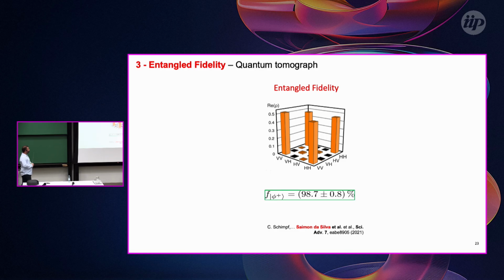Okay, the third thing that we look at is the entanglement fidelity, which is measured by doing quantum tomography. In general, we already know that these gallium arsenide quantum dots generate a Bell state, the phi plus. Generally, with this fidelity you want to measure what your experiment is giving you compared to what we are expecting. This means we have a Bell state, and we measure how close it is to what we are expecting. For these gallium arsenide quantum dots in 2021, we demonstrated that this value is almost 99%. This fidelity is related to some quantum communication experiments. A high fidelity means that you decrease the errors that can be generated during this kind of experiment.